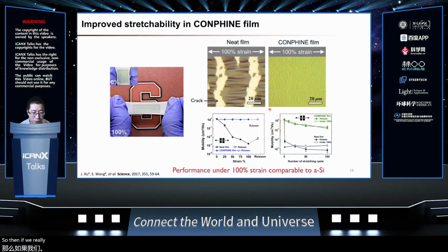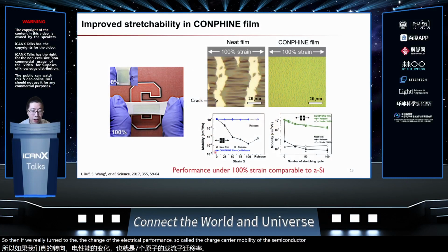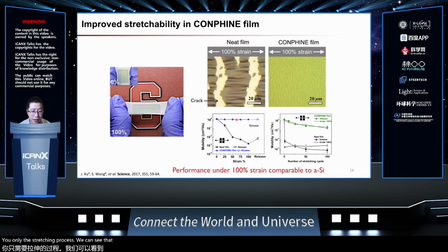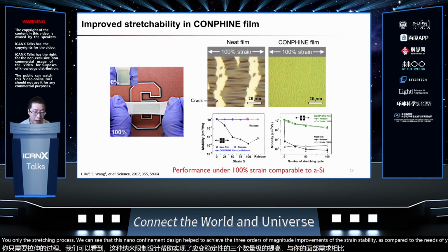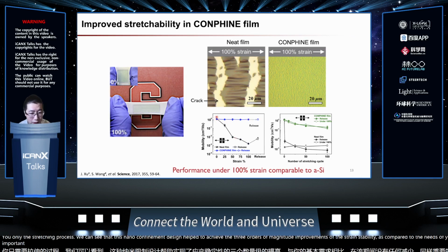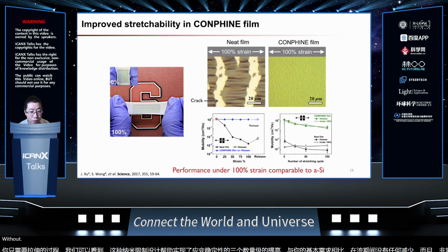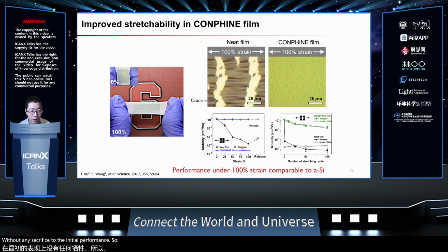If we turn to the change of the electrical performance, the so-called charge carrier mobility of the semiconductor during the stretching process, we can see that this nano confinement design helped to achieve 3 orders of magnitude improvement of the strain stability as compared to the neat film, basically without any decrease during the strain. And also very importantly, there is no sacrifice to the initial performance. So basically we have been able to maintain the amorphous silicon level semiconducting performance at even 100% strain deformation. So this has been our first step of achieving the high stretchability for the confined film.